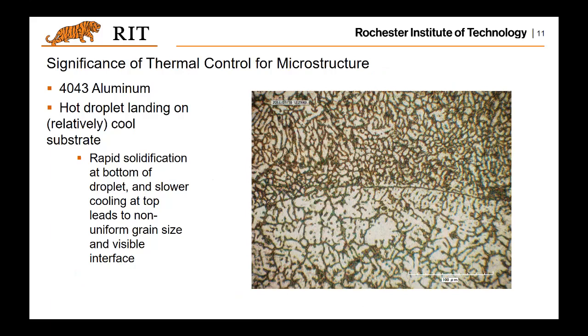And there will be some thermal control for this process, such that the microstructure will be different. So when a hot droplet lands on a substrate which is at a cooler temperature than the droplet, something happens at the microstructure level. Basically, there will be a rapid solidification at the bottom, because it's cooler. So solidification will happen faster at the bottom, and slower solidification or cooling at the top. And what it does is create a non-uniform grain size. As you can see, this shows you the difference. The grain size for this one is relatively large and this one is smaller, and there's a clean interface between the two.